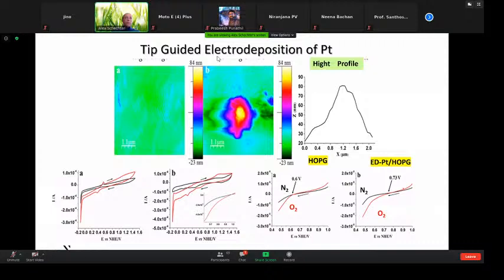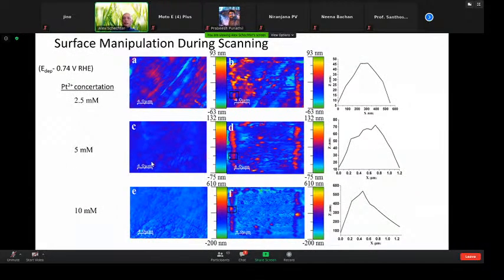So we took it one step further, and we were able to deposit platinum as we wish while scanning the surface, and you can see a very nice alignment of the platinum. The reason for this alignment is the fact that while forming these particles, we also drag them using the tip. The tip is dragging the platinum to the end. We can control the size of the particles and the dispersion by controlling the molarity, or the concentration, of the platinum salt.